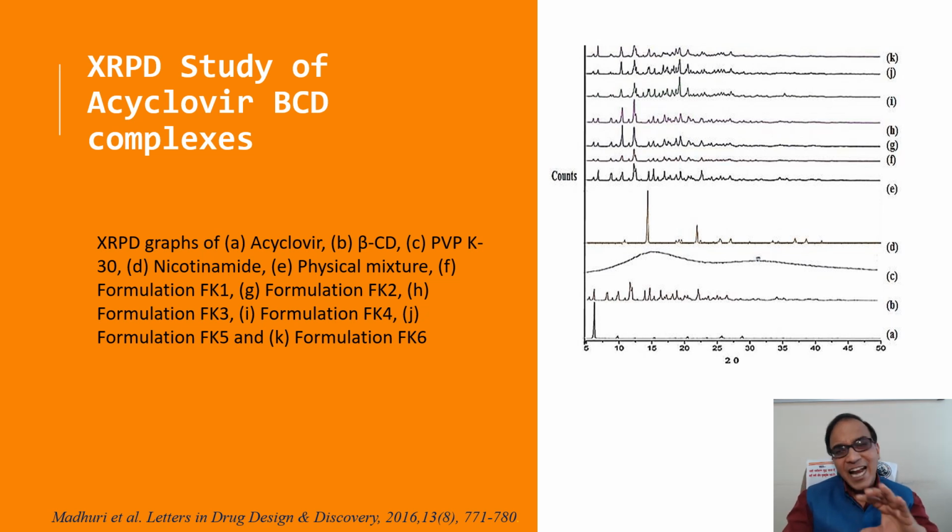So we can compare this with the DSC. We can correlate this data not only with the DSC but also with the scanning electron microscope, the surface morphology. We can compare how the changes are correlated with the DSC. If there is a change in the endothermic peak, and a complete disappearance of the endothermic peak in the DSC, certainly the change will be there in XRPD. And this will be in good tune.